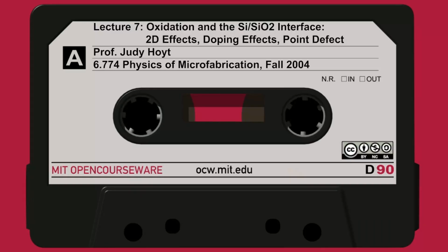So let's go on to slide 28. And this is the diagram I just went through. These are the different processes we talked about that contribute to this oxidation-enhanced diffusion. So it's this generation at the interface where I'm oxidizing, and the recombination, the balance of G and R, generation and recombination, that determines what your net flux of interstitials is into the bulk, away from the surface.